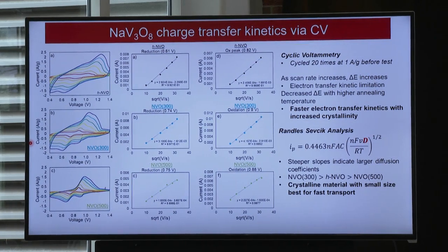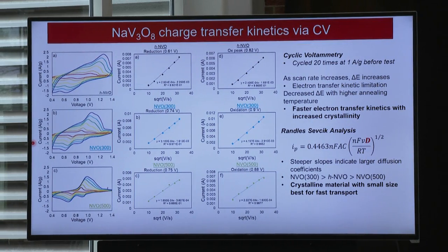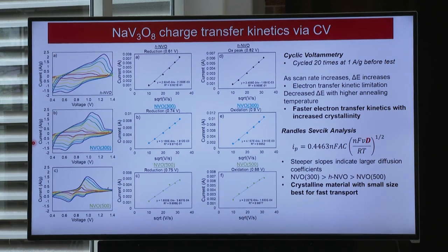We started running electrochemistry of our three different materials and saw that the reversibility in terms of electrochemical reversibility was different for the three materials. And by electrochemical reversibility, what I'm really looking at is delta E peak. So where is my potential peak and how closely are those peaks spaced for oxidation and reduction?